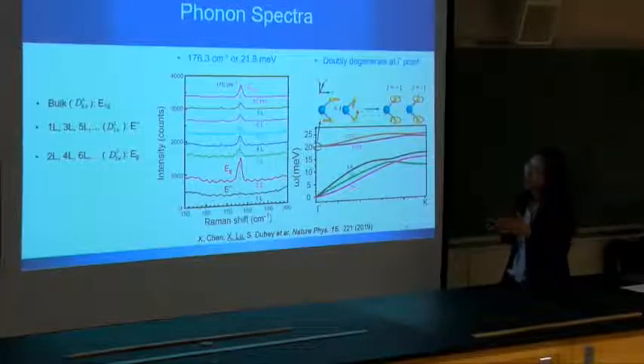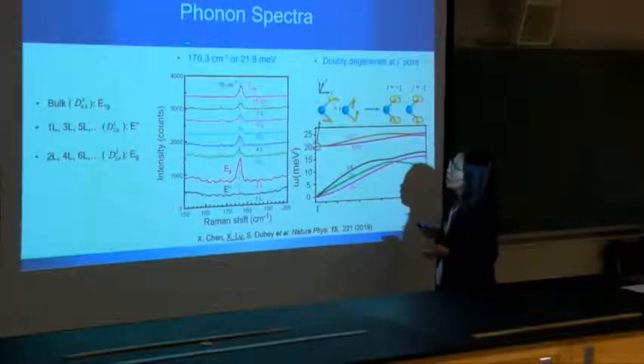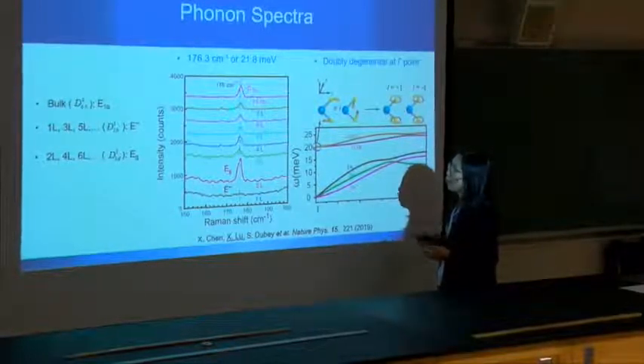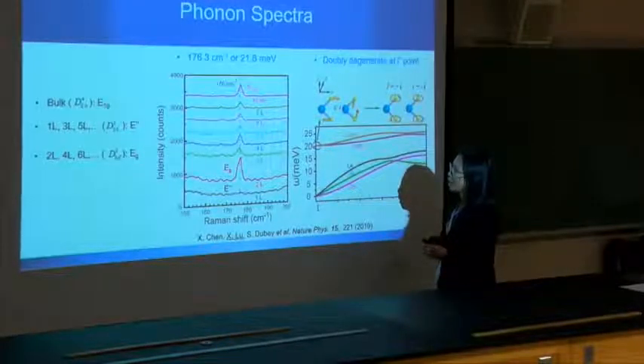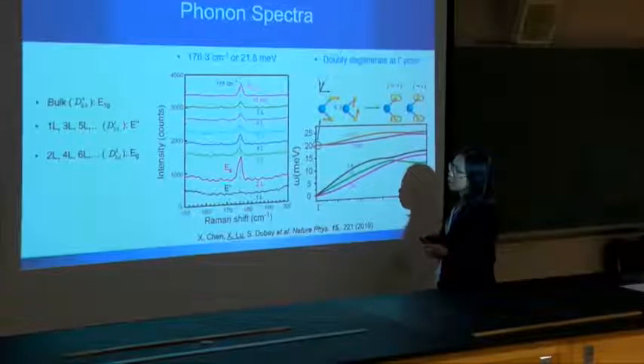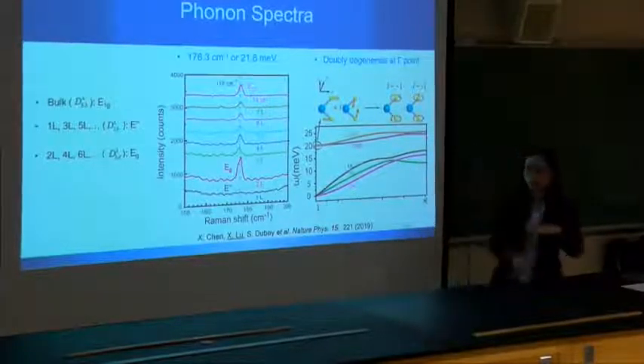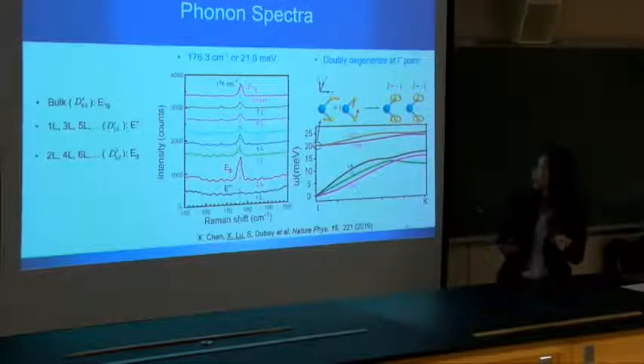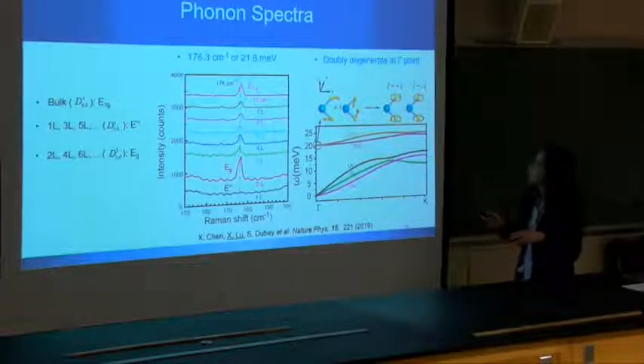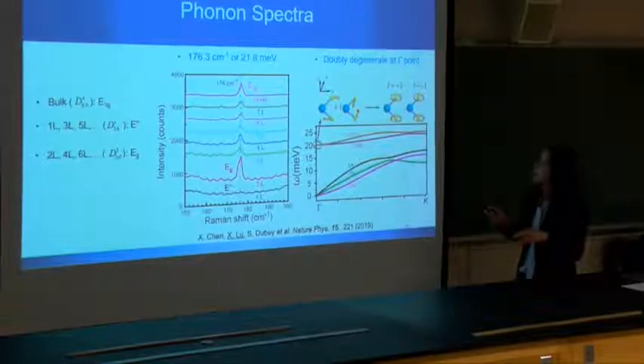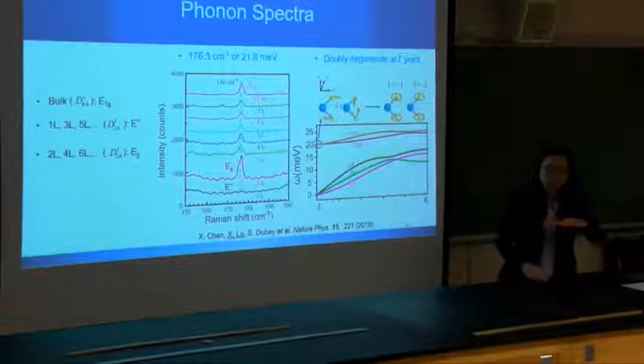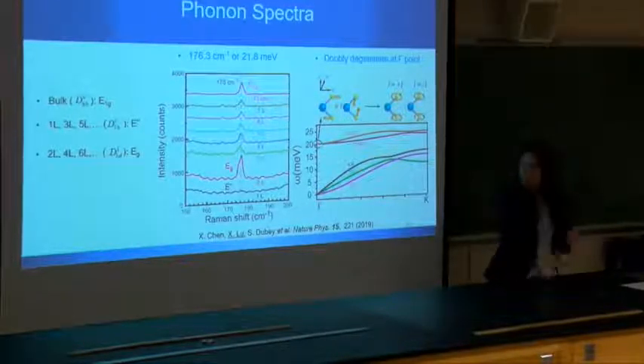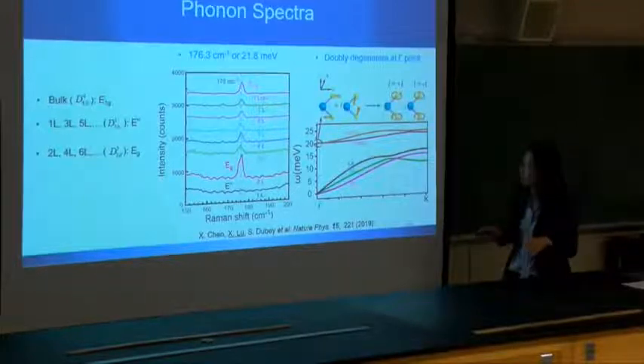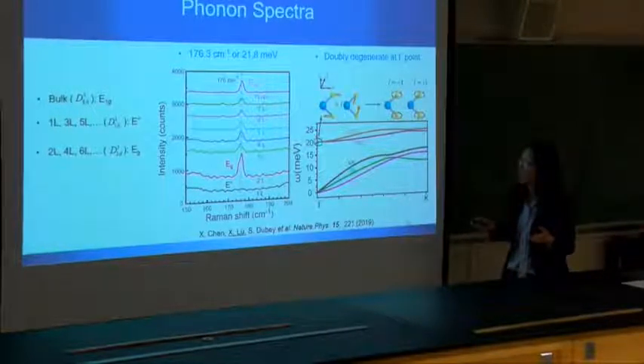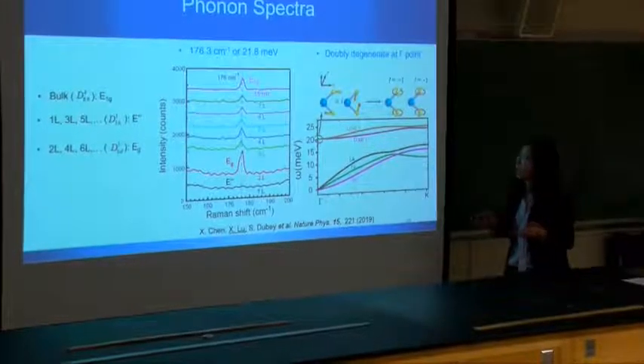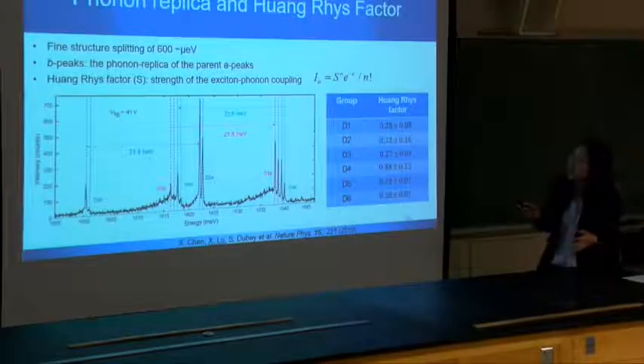So with that in mind, we go to measure the Raman spectrum. Indeed, in tungsten diselenide, from the Raman spectrum, exactly at 21.8 milli-electron volt, we see a phonon with E symmetry. So it's an in-plane vibrational mode. You can see here that this is the metal, tungsten. So the selenium, the chalcogen, moves in plane, either in the X direction or the Y direction. So it's like a degenerate mode, as you can see here from the calculated phonon dispersion. It is a degenerate mode at the gamma point. So yeah, that's a phonon replica.